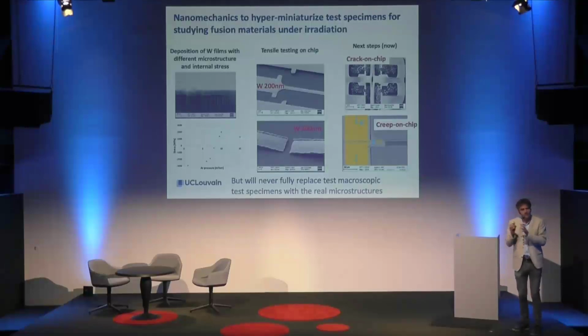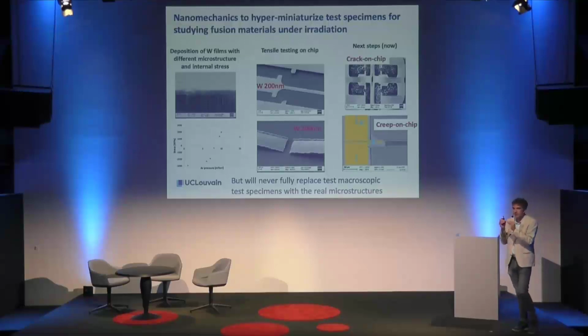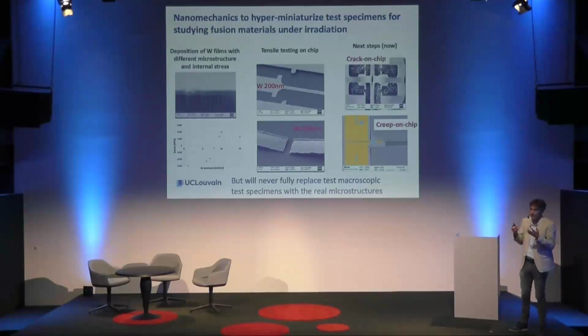Another thing of interest and quite original, I think, is to try to miniaturize the test. You know that we don't like, especially when we have to irradiate the material, to see how the neutron irradiation is influencing the material behavior, how it's embrittling the materials. We don't like to have too big volumes which are activated, so we like to make small test specimens, and these ones are extremely small.